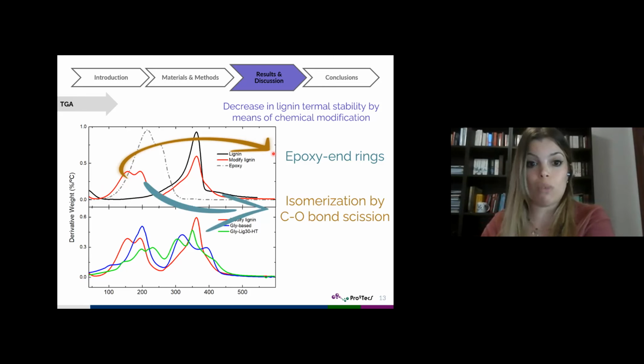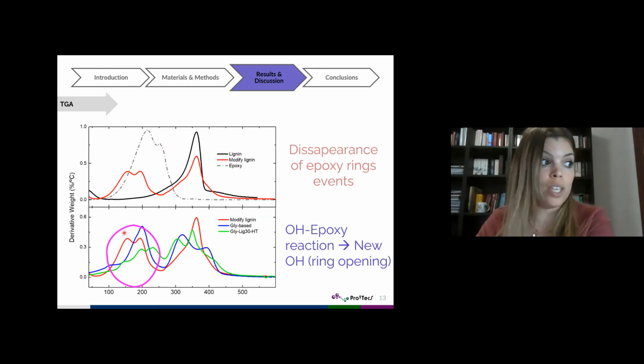On the other hand, the chemical interaction between NADES and modified lignin could be verified also by the disappearance of these two new peaks in the modified lignin, two new thermal events related to the existence of free epoxy rings, which proves the reaction with the hydroxyl groups contained in the NADES mixture, leading to the formation of new secondary hydroxyl groups as a consequence of the epoxy ring opening when the reaction between both groups is carried out.